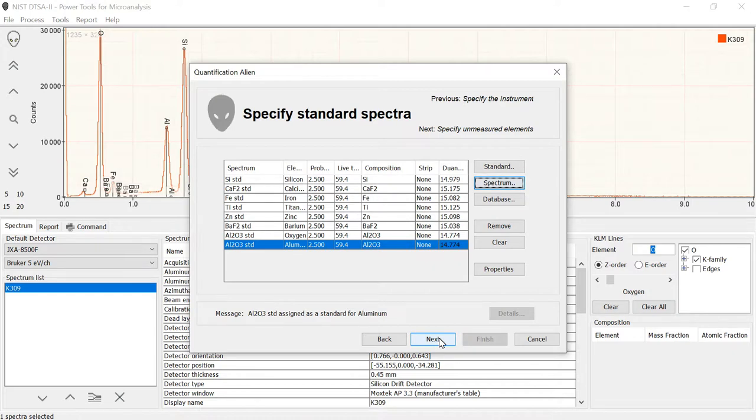So, having selected the spectra, you can see that the probe current is specified in each one of them. The live time is also available. And you can see it also calculates what the Duane-Hunt limit is. Since this should be nominally about 15 kilovolts, and these are roughly there, you can see that some of the ones, like this alumina, which is an insulator, the Duane-Hunt measured off of it is a little on the low side, and this isn't too surprising